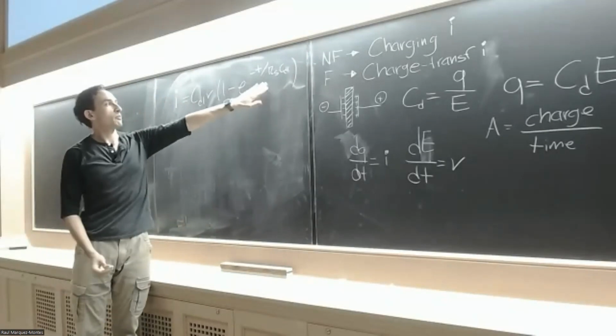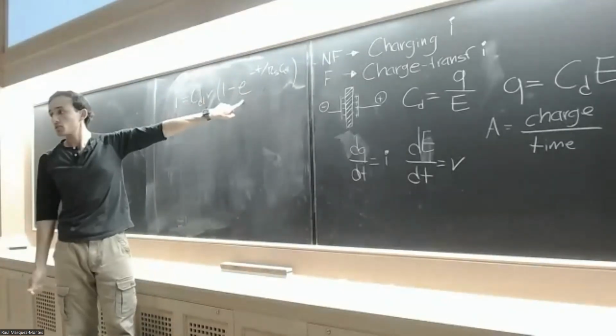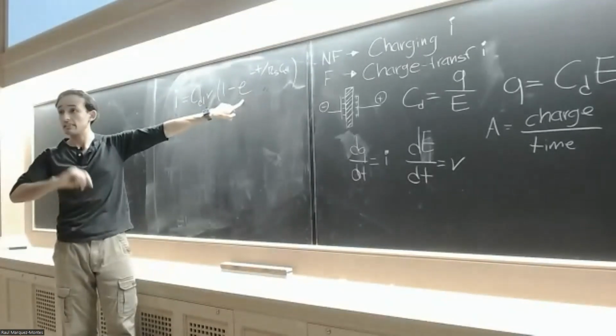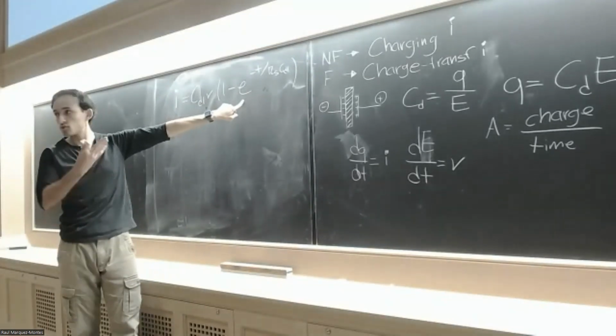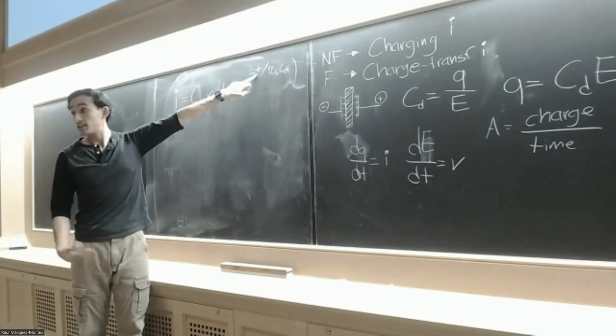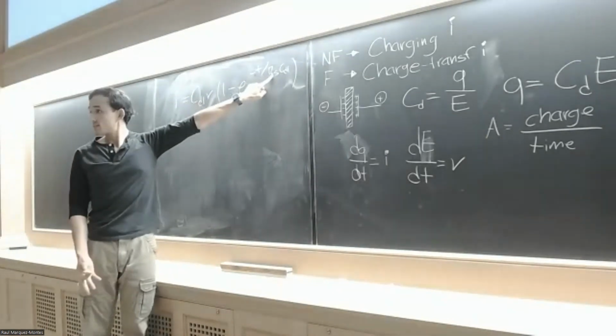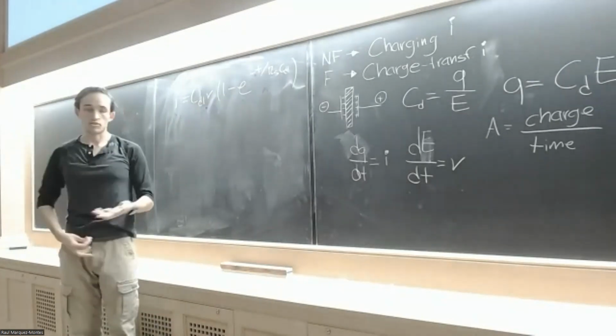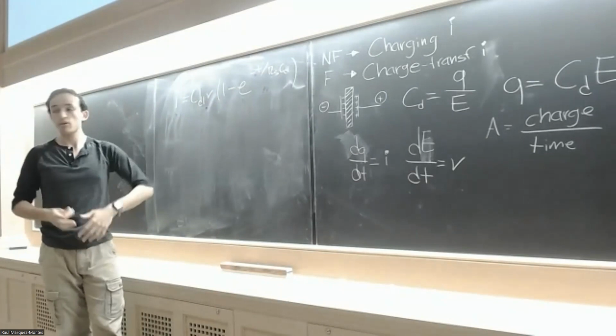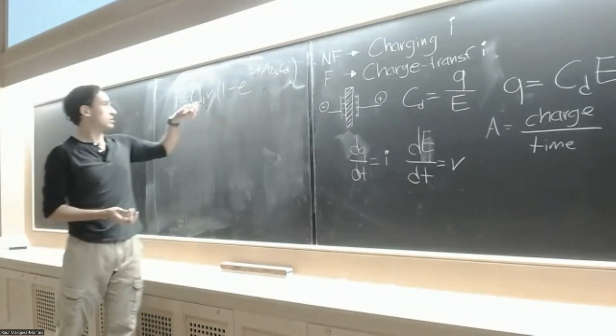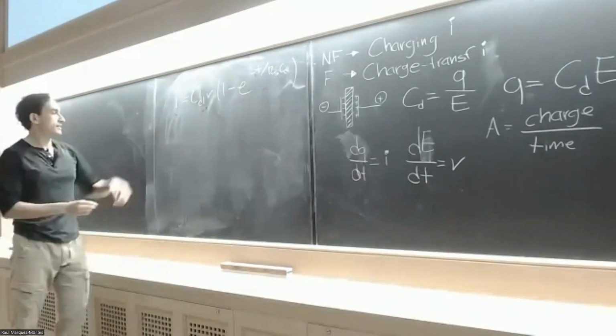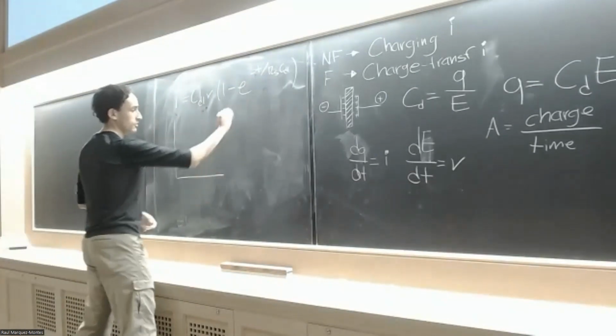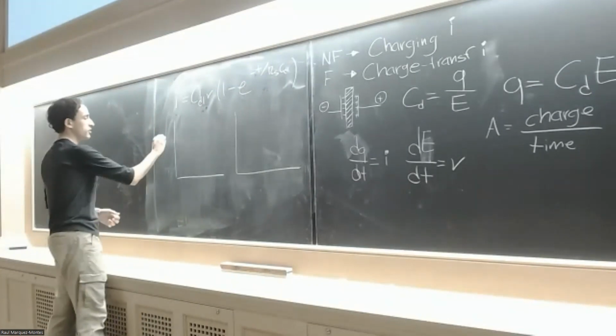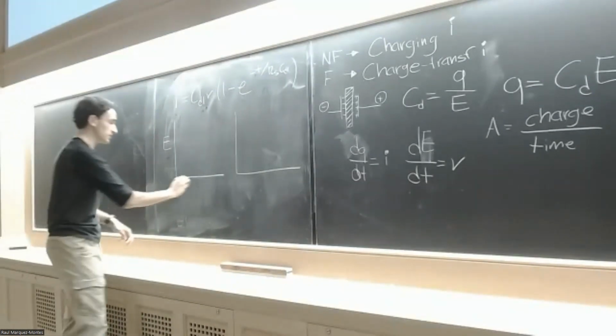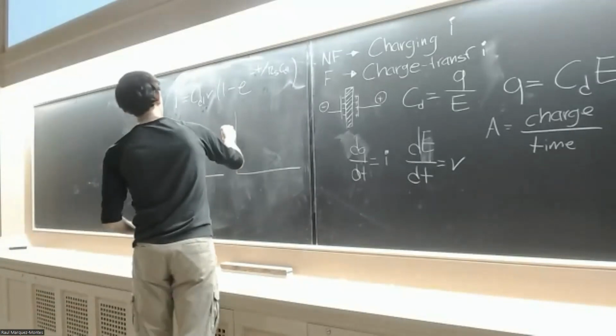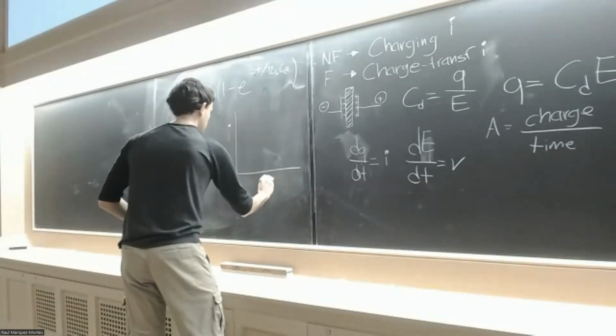So this term here is composed by the time. This exponential term is basically showing that there's some kind of decay or stabilization. And I will show you the plot in a little bit. It depends on the time, it depends on the resistance of the solution, and also it includes other terms that could be contributing to the resistance. And again, the double layer capacity. So if we plot this, we will see something like this. I will show you two plots here. The first plot is the potential against the time, and the second plot is the current against time.